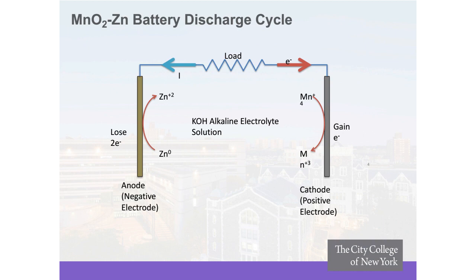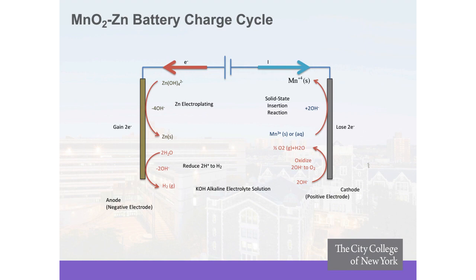In the first example that I've mentioned, we are focusing on batteries that are using the chemistry of the manganese dioxide zinc metal anode. In these cases, I'll focus exclusively on the anode for the purposes of this presentation. We basically have metallic zinc that upon discharge actually corrodes, oxidizes from Zn0 to Zn2+, and the Zn2+ species are actually soluble in the alkaline electrolyte that we use. During charging, these species actually replate onto the anode by accepting 2 electrons, and they form metallic zinc again.